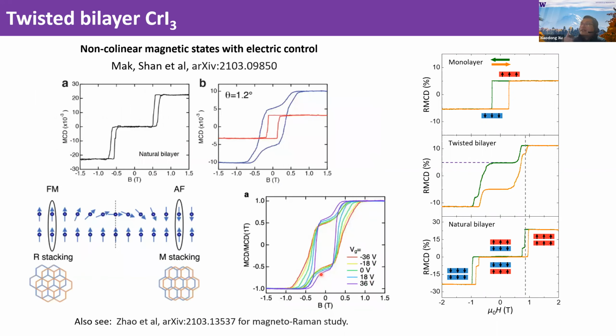Our data is also consistent with data from Kim Fai Mak and Jie Shan's group. They have the same type of device, and their optical measurements are very consistent with what we have here. So the short conclusion is, if you stack a monolayer on top of a monolayer with a small twist angle, you'll have a mixture of monolayer and bilayer behavior.